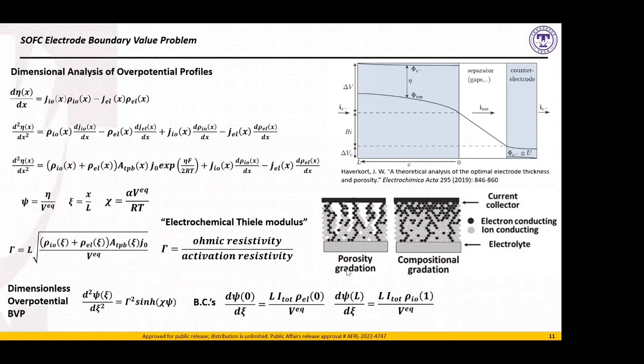The overpotential is related to the difference between the Fermi level of the electrons and the ionic component of the potential within the electrode. So we define this differential equation here at the top, where the gradient of the overpotential is equal to the ionic component of the current density multiplied by the ionic component of the resistivity minus the electronic component of the current density multiplied by the electronic component of the resistivity. If we take the second derivative of this, assuming that we have a cell which changes its composition throughout its thickness, then we have this differential equation that is laid out here on the screen.